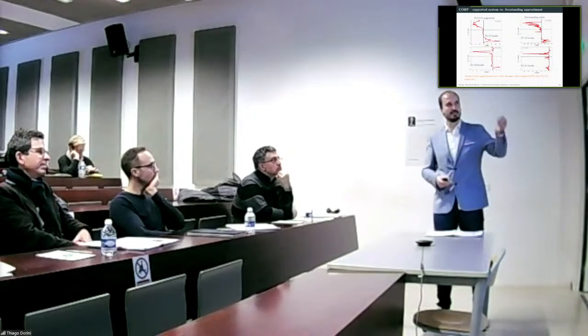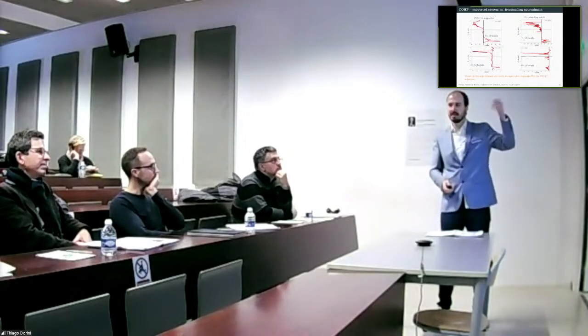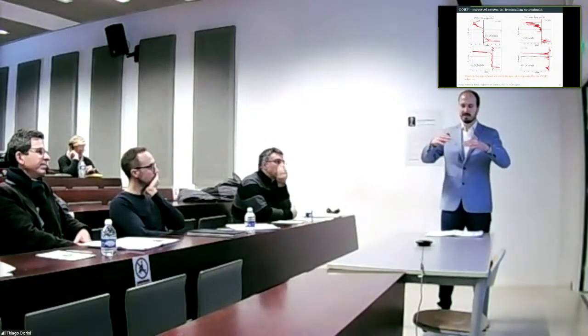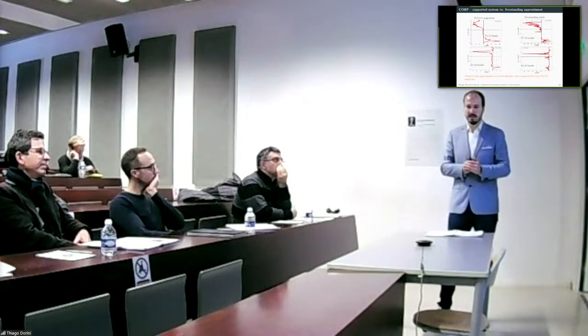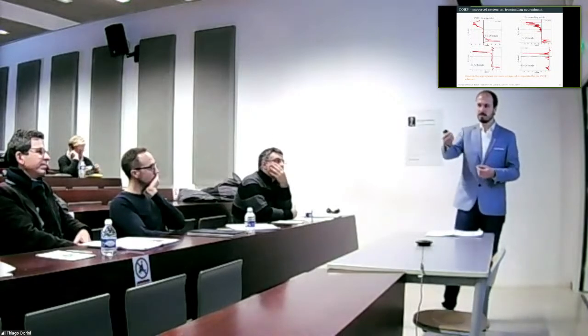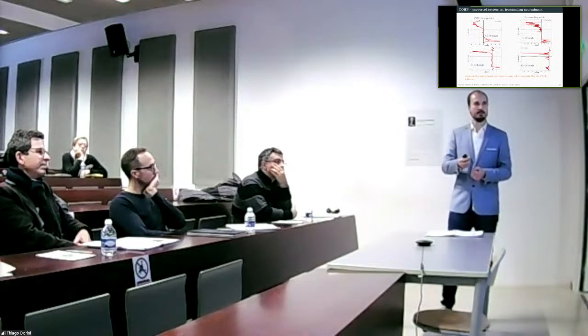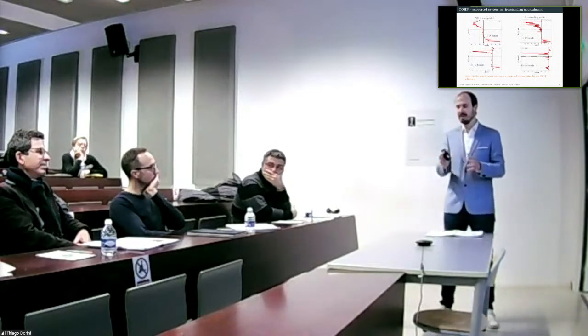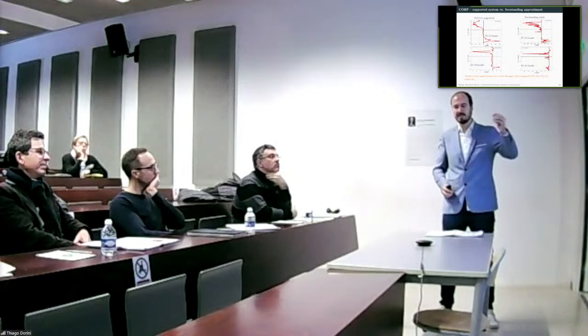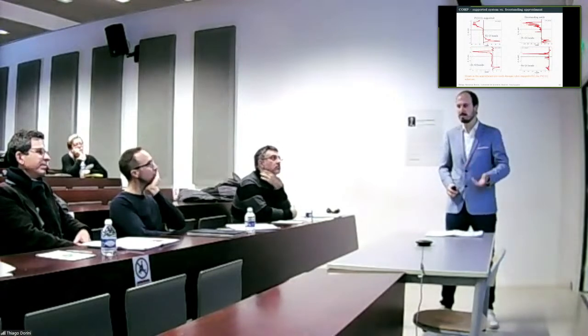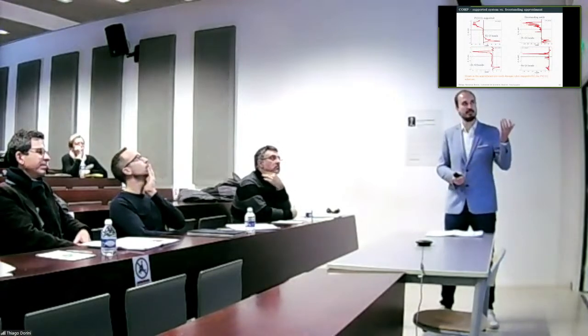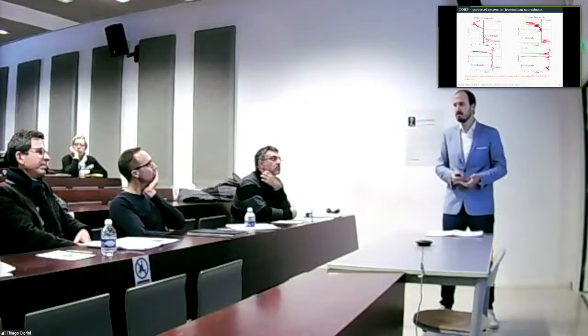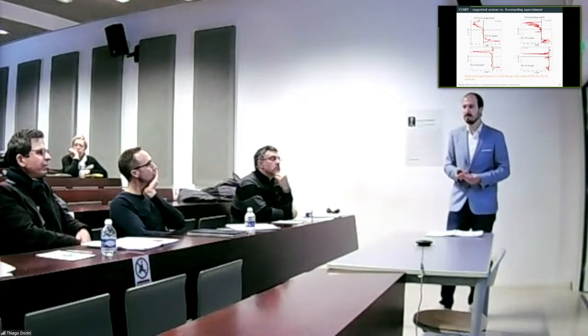So this leads us to believe that what may play a role is the titanium bonds, and also there's this relaxation of titanium atoms closer to the platinum. And the charge transfer goes from the titanium, especially the titanium to the platinum. So we have all these three elements that lead us to believe that this is the bond that actually is the most important. And according to these calculations, they are quite strong. That's what I think about this system.